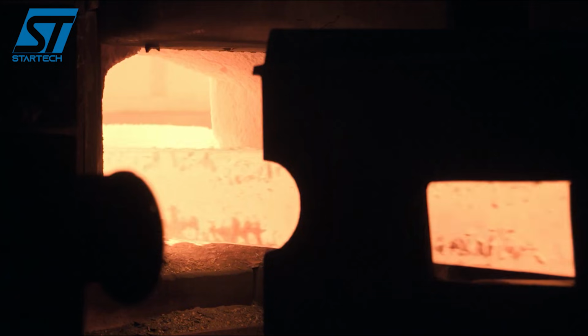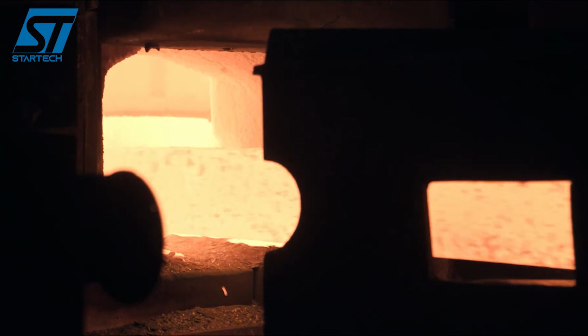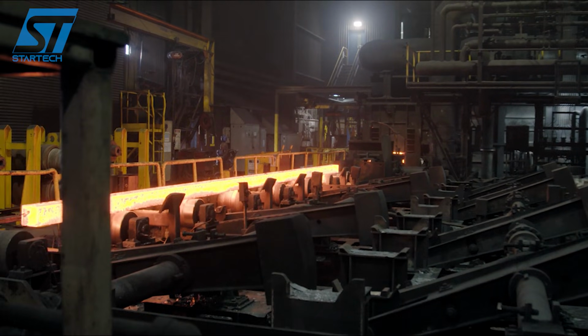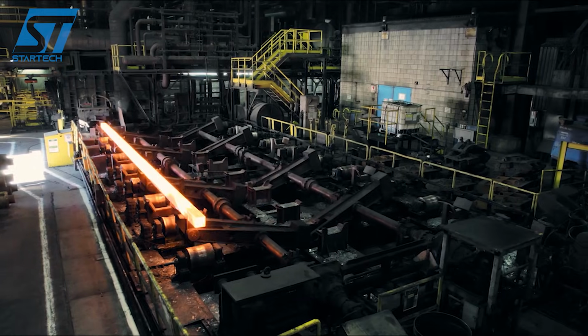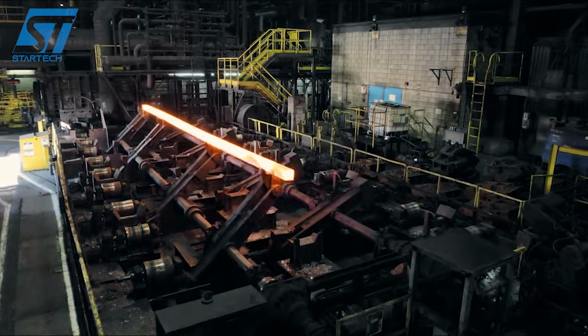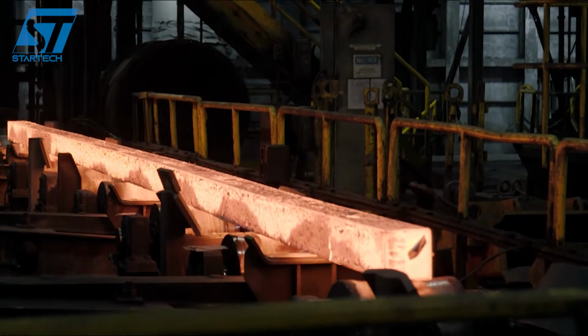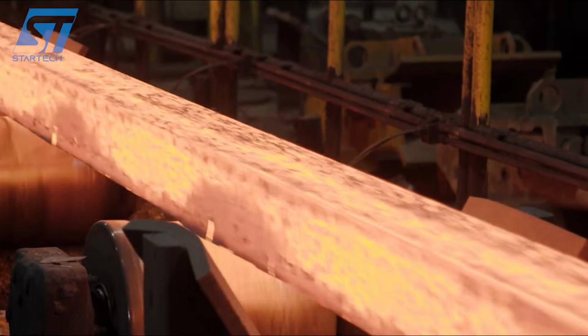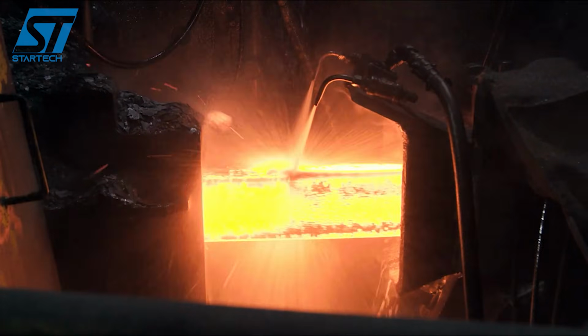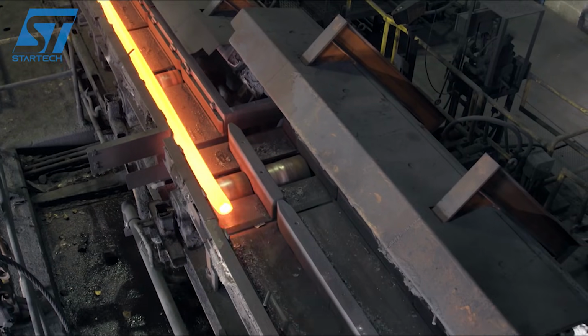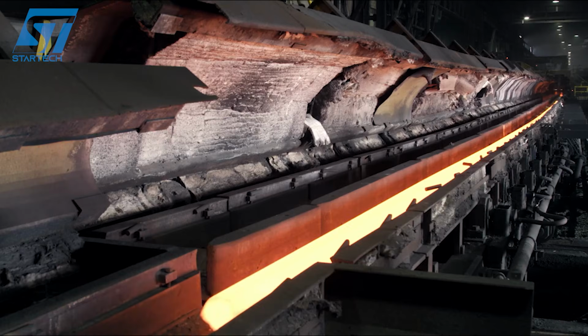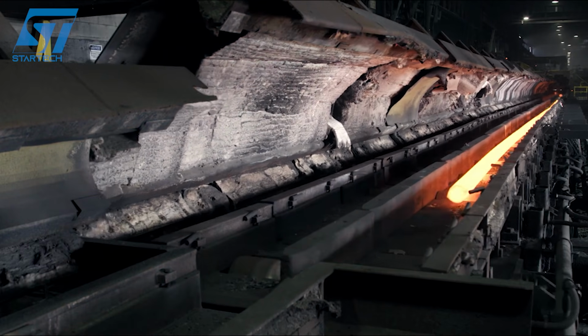At the exit, the wire rod is traveling at speeds up to 100 meters per second. That's roughly 220 miles per hour, and it's coiled by a laying head, which loops the rod into neat rings before it lands on a Stelmor conveyor for controlled air cooling. That cooling rate determines the final mechanical properties of the steel. Slow it down, you get a softer wire. Speed it up, you get higher strength.